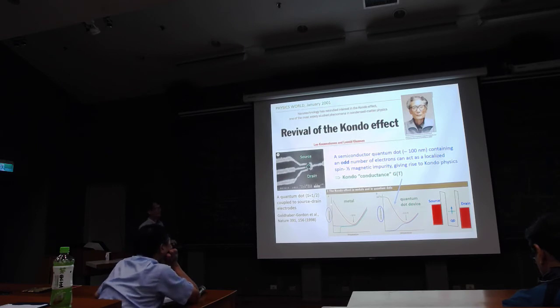And they do observe Kondo conductance, but in this case, it is conductance. Because the coupling of the conduction electron spin with this local moment actually enhances transmission. So the conductance is increased, but the functional form is exactly the same. In the original Kondo physics, because conduction electrons scatter off this local moment, resistivity increases with decreasing temperature. But in quantum dots, conduction electrons are just coupled with this local spin and transmission is enhanced, so the conductance actually increases. So in the 1990s, there was a new development that people call the revival of the Kondo effect in semiconductor quantum dot experiments.